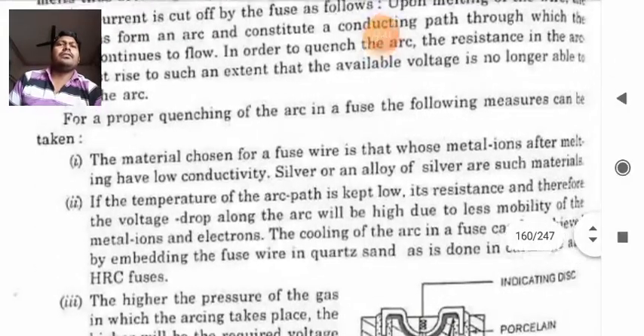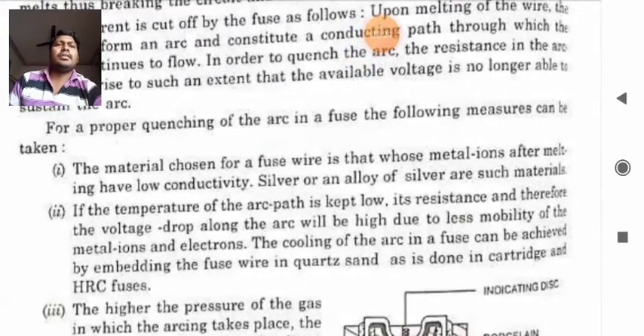The material chosen for a fuse wire is one whose metal ions, after melting, have low conductivity. Silver or an alloy of silver are such materials. If the temperature of the arc path is kept low, its resistance, and therefore the voltage drop along the arc, will be high due to less mobility of the metal ions and electrons. The cooling of the arc in a fuse can be achieved by embedding the fuse wire in quartz sand, as is done in cartridge and HRC fuses.